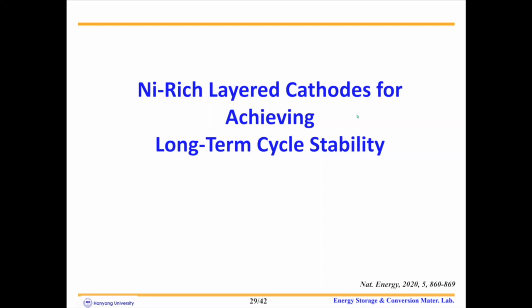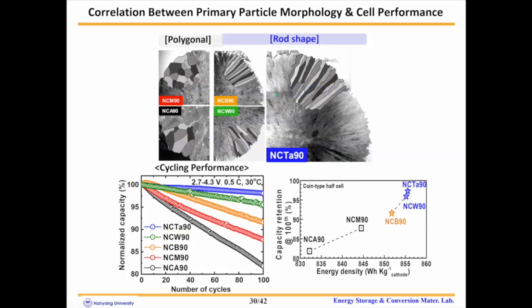After verifying the microstructure modification effect, we further investigated to find the optimum microstructure for achieving long-term cycling stability. This figure shows the dopant effect on the microstructure of the cathode primary particles. As you can see, the microstructure varied from large equiaxed polygonal type primary particles to fine needle-like particles. The cycling stability is strongly dependent on the particle microstructure. Among the various dopants tested, the tantalum-doped cathode material shows the best cycling performance.